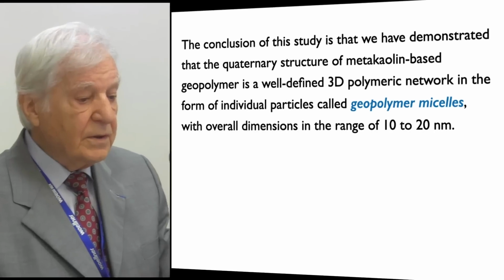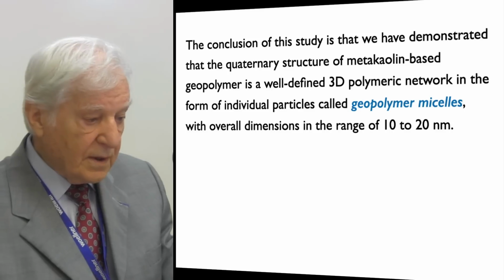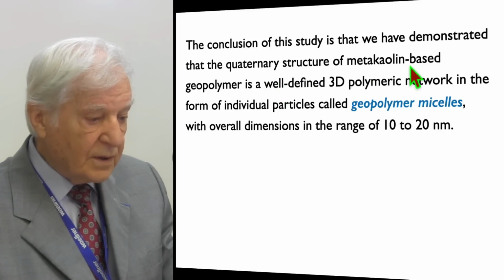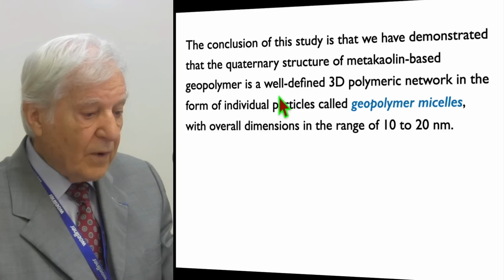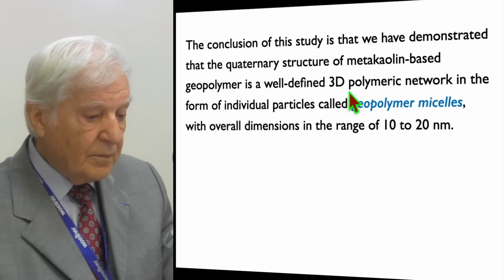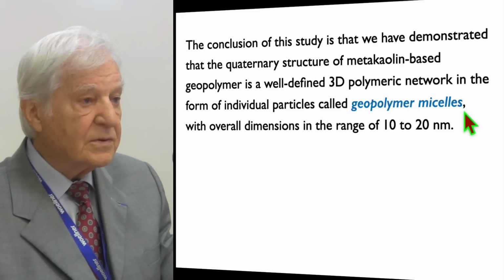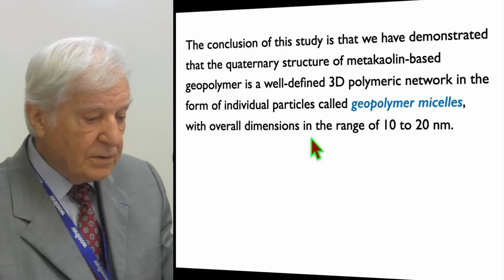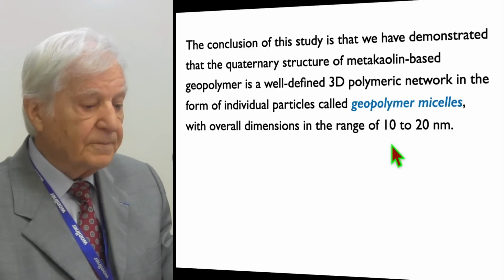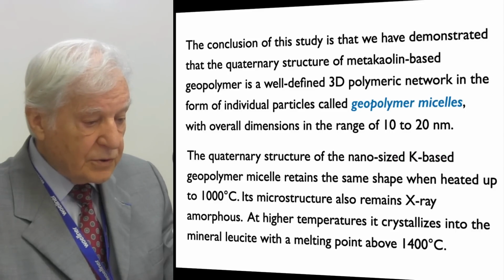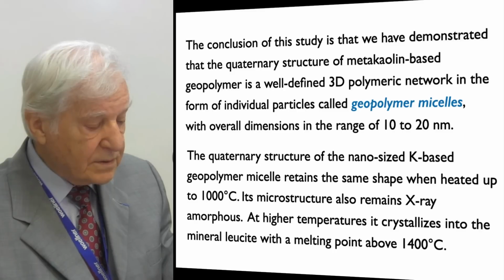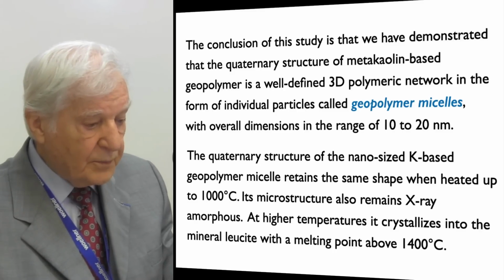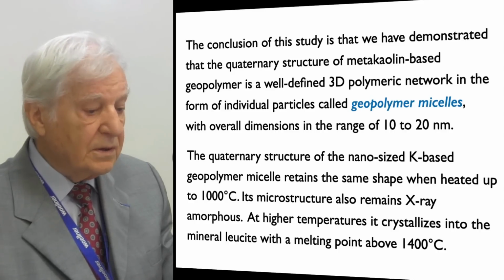The conclusion of this study is that we have demonstrated that the quaternary structure of metakaolin-based geopolymer is a well-defined 3D polymeric network in the form of individual particles called geopolymer micelles, with overall dimension in the range of 10 to 20 nanometers. The quaternary structure of the nano-sized potassium-based geopolymer micelle retains the same shape when heated up to 1000 degrees C.